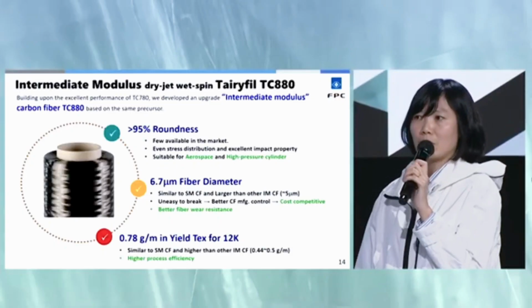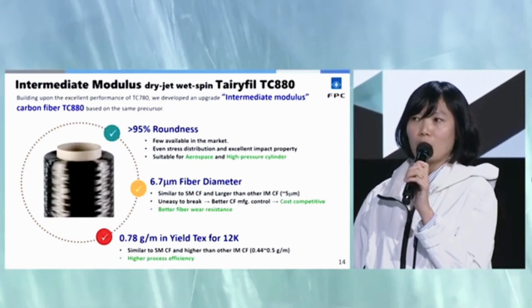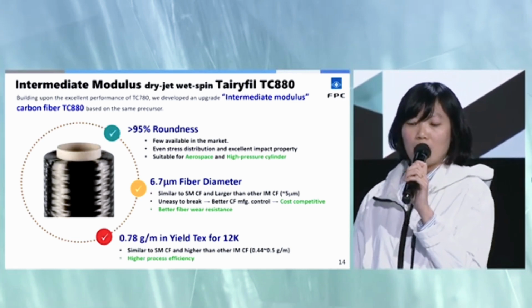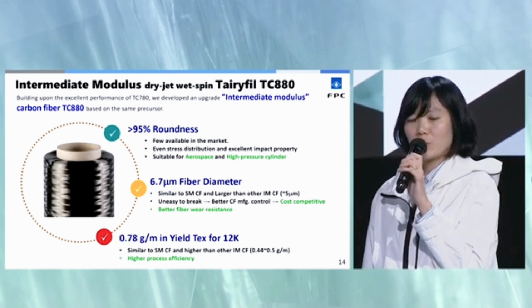So now we have arrived at the focal point of today's presentation, the new product, TC880. Building upon the TC780, it uses the same precursor technology, and it shows higher than 95% roundness. Such dry jet intermediate modulus fiber is not available everywhere in the market. It has higher impact resistance, which helps for aerospace, and the longer elongation and higher strength is beneficial for pressure vessels.